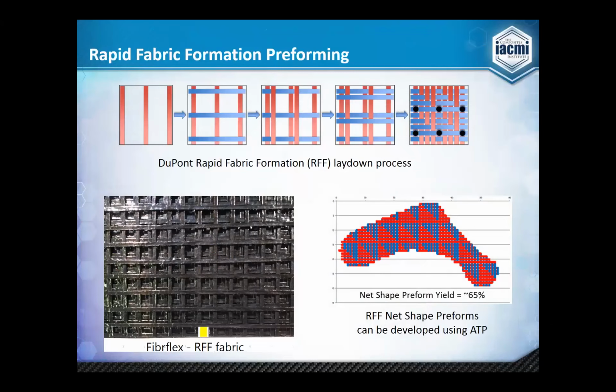And then the opposite direction fiber, the 90s in this case, are placed on top of that with a similar spacing. And then you come back with an offset and place the tows in the opposite direction, and so on and so forth, till you get a completed cell structure, as you can see on the right-hand side, which is what we call a 4x4 tow cell. You can also see little black dots.